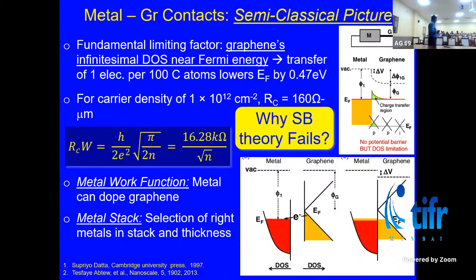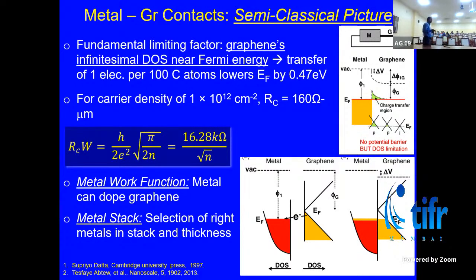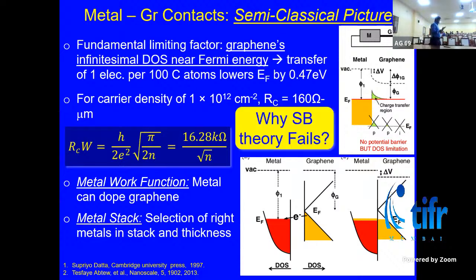Now, what we found was that this concept fails, because it depends on this barrier. If I reduce the carrier energy, the carrier is going to see a larger barrier effectively. How do I reduce the carrier energy? At room temperature, the carrier has statistically around 25 millielectron volts of thermal energy. If I cool down the system, that energy goes away, which means the carrier is bound to see a larger barrier, and therefore the resistance should increase. But what we saw, and also the world observed, but nobody analyzed it.